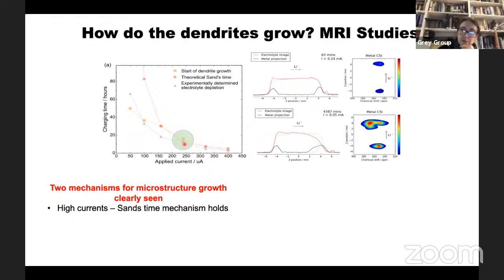And we can see that it all works very well until you get to very low currents. At low currents, you would predict that you would never get this depletion, and yet you still get the dendrites. And this is what is shown in this picture here. The movie for some reason isn't working, but you can still see it's forming this dendritic structure.